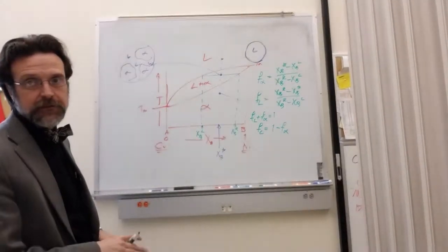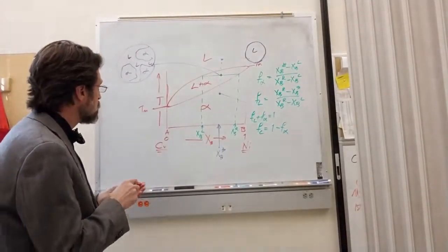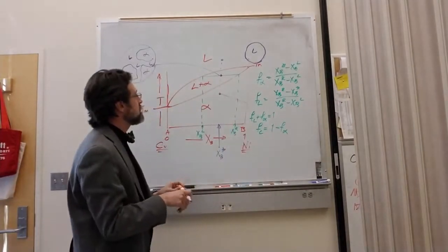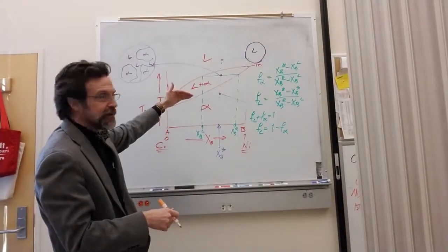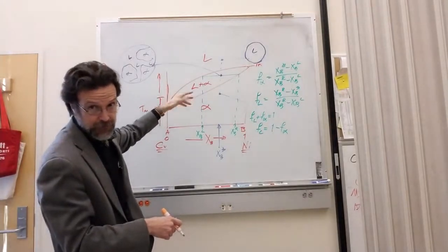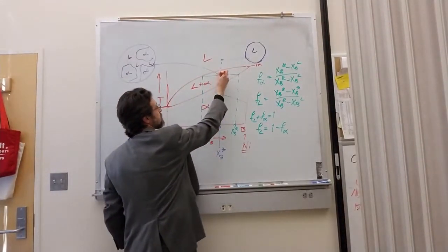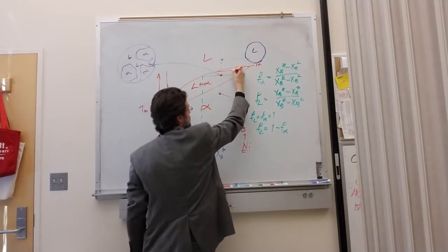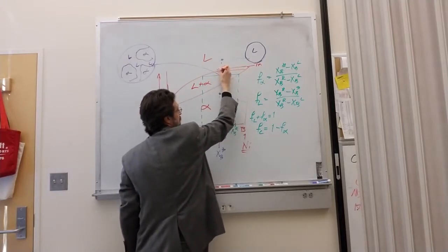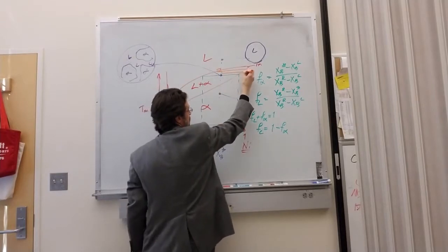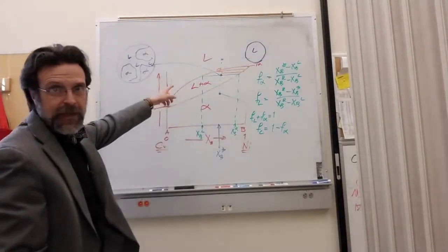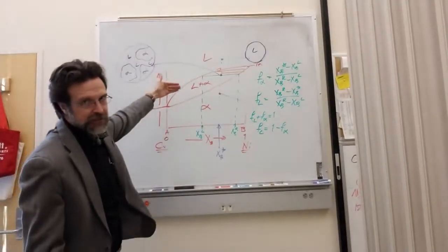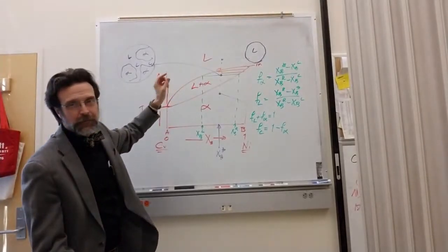So why is it that it works this way? Well, the reason it works this way is you can imagine the point where we just barely cross from liquid into the two-phase region, right up here. And if we just barely crossed, and we draw our horizontal line, we have a little part here, and we've got a big part here. And at the same time, we know that it was just liquid, and we just had the first little bit of alpha form, right?